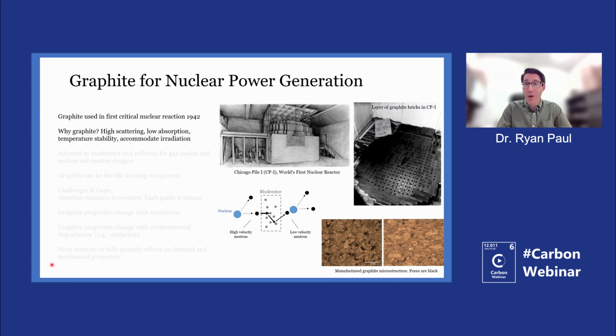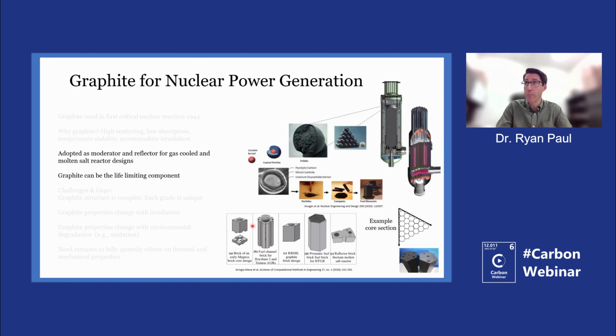There is a lot to be said on other applications too, and in fact, even for nuclear power generation. Graphite has been around from the beginning here as well. Graphite was used in the first critical nuclear reaction in 1942, because graphite does have a high scattering cross-section, low absorption cross-section, high temperature stability, and the ability with the porosity to accommodate irradiation. So graphite has been around from the beginning of the nuclear age and continues to be.